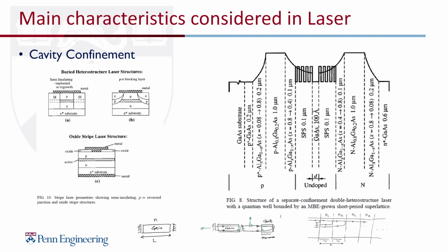This photon confinement will result in less loss during the resonance, which would also reduce the energy required for the laser. And furthermore, people have now introduced a short period superlattice in the active layer, like Figure 8 shown here. They succeeded in obtaining the desired index profile in the waveguide region and creating a barrier against the motion of these dislocations into the active zone. Therefore achieved excellent surface morphology simultaneously with a high internal quantum efficiency.